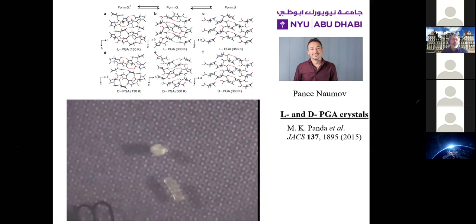And what you see is that as you heat them, the polymorphic transition causes the crystals to jump off the plate, and yes, they kind of disintegrate when that happens. Of the three samples we had here, two of them jumped off the plate. One of them never will, because this is not an isotropic type of transition.